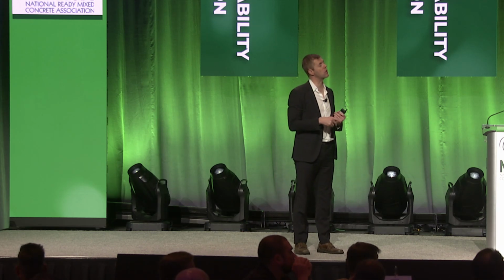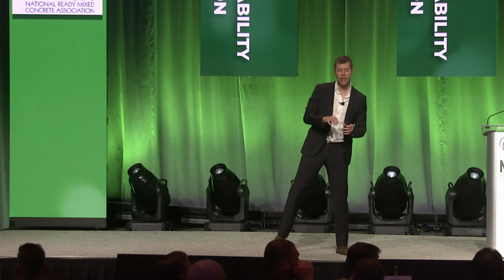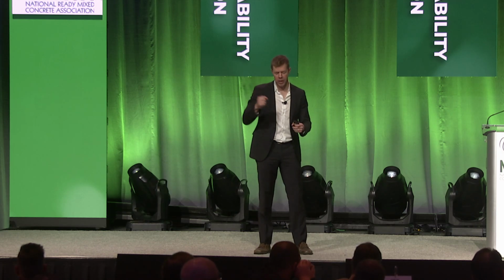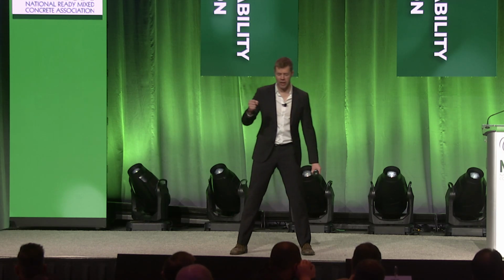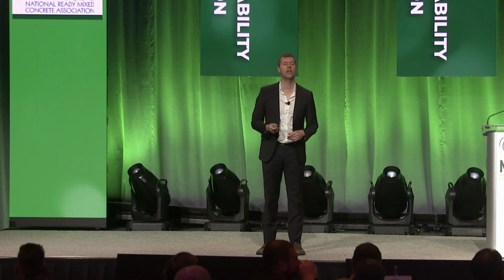Here's how the test works. On the left-hand side is the mass. On the right-hand side, on the bottom, is the time. And what you're doing is you cook it. You have to open it up. You have to break it up. Hopefully you don't lose anything. Put it back in and cook it for 5 more minutes and do it again, and again, and again. And in the test, the way the test works is you only use 1,500 grams.